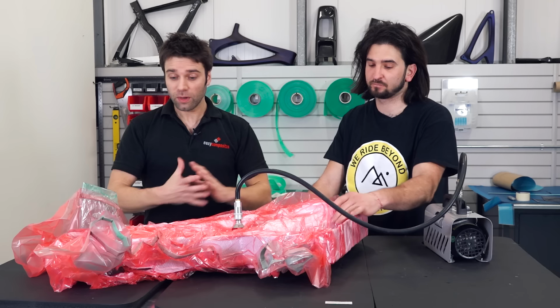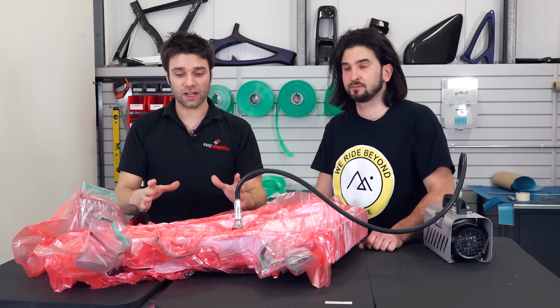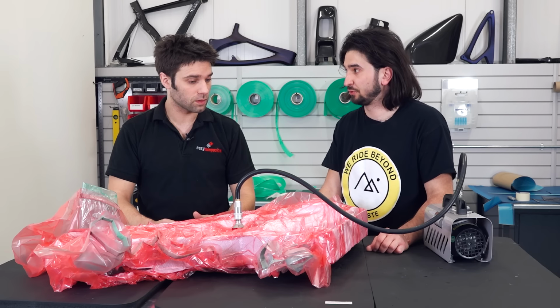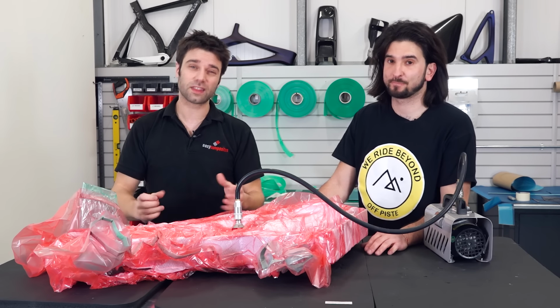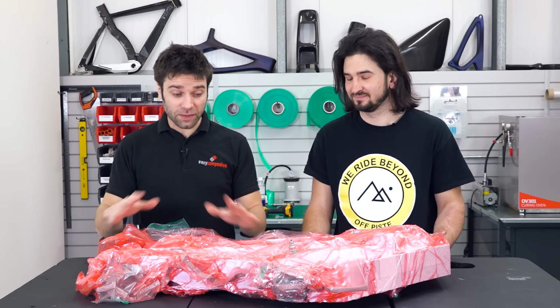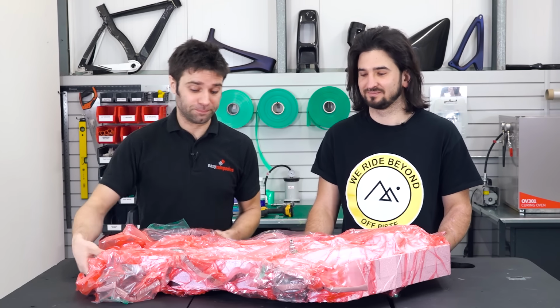So it's all bagged up now, so this is basically ready for a cure, but before that we're going to do a bit of a debulk. How long are you going to leave this under vacuum? Well, we're going to leave this overnight and put it in the oven tomorrow morning. Debulk overnight, that gives us opportunity to make sure that the bag's holding a perfect seal and gives extra time for the laminate to fully consolidate. So we've left this under vacuum debulking overnight, and so now all that's left is the final cure.